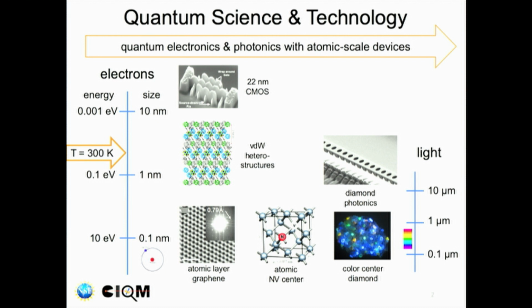Another thing that happens is that the energy of the transitions goes up to energies of electron volts. And it turns out that's optical photon energies. And so it moves the transitions that you're seeing from something down in microwaves and things that sound like exotic lab physics to something that you can actually see. And so that's another change.